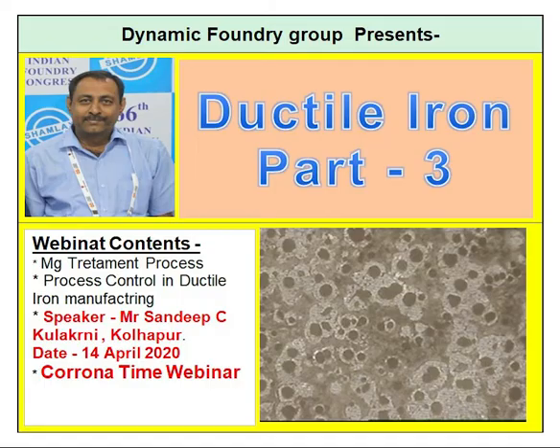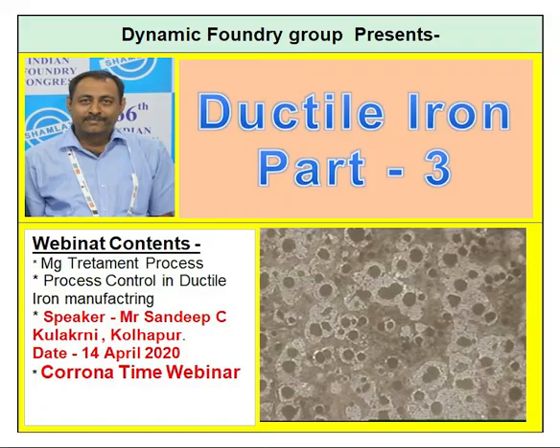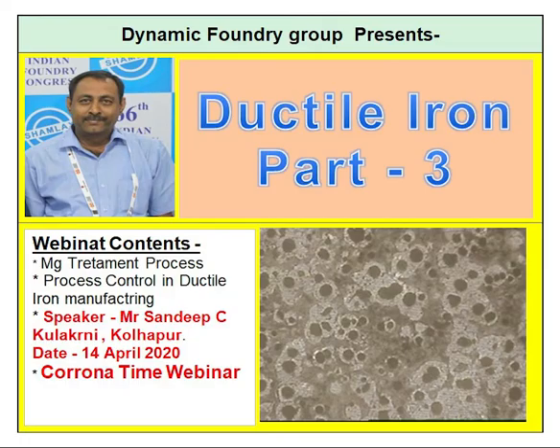The spectro sample is very important to understand the final carbon, final silicon, final copper, final manganese, and most importantly your residual magnesium. The residual magnesium will guide you for the next heat. If residual magnesium at the last box is low, you have to investigate: check your base sulfur, your tapping temperature, the ladle condition, whether you exceeded the pouring time — identify what went wrong and take the decision based on that result.